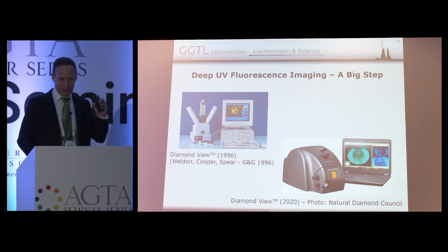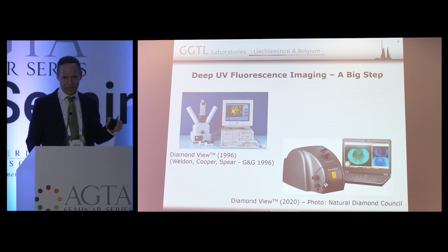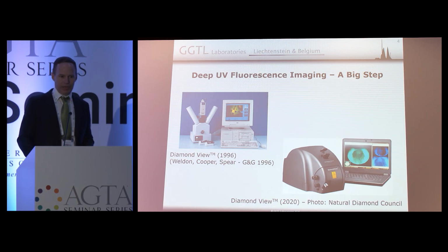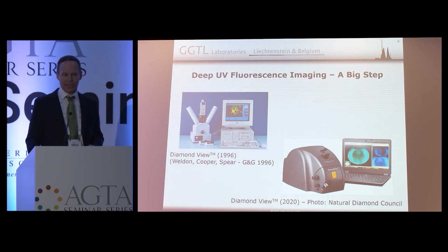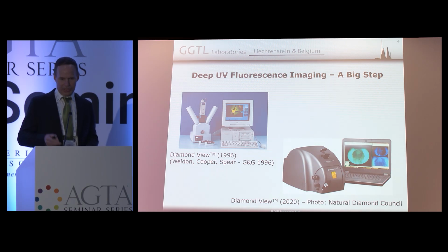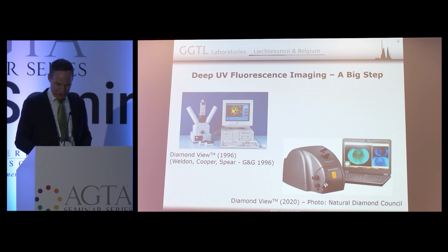So pure diamond absorbs light at exactly 225 nanometers, or just below. The rest of it is transparent. So by using this kind of light source, you're making it possible to see surface-related fluorescence much more easily and readily than with any other UV source. That's why they started using this excitation exactly at the band gap energy.